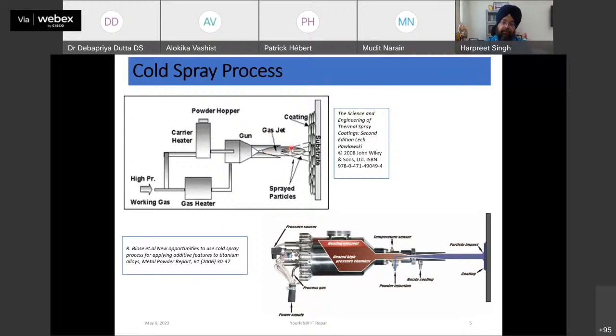where we have the metallic powder particles. So we use the powder to make our final product, which is also the case in most of the additive manufacturing technologies. But here what we do is propel this powder through a very special kind of convergent divergent nozzle. This nozzle has been specifically designed to achieve supersonic velocities of some gas. Here in this case, most of the time we use some cheaper gas like nitrogen. So this nitrogen can be accelerated through this nozzle. Those who are in mechanical engineering will understand that if we have a converging diverging nozzle, we can always accelerate the fluid to supersonic velocities, meaning more than Mach number 1.